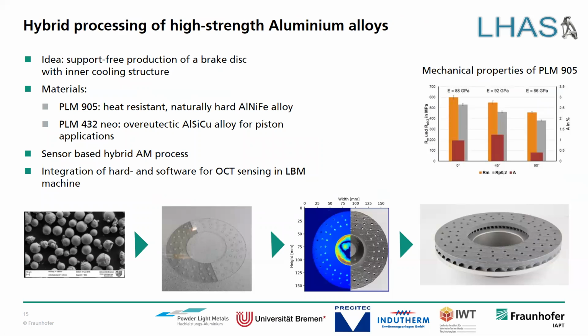A next project example that I just want to touch briefly on is the development of aluminium nickel iron and aluminium silicon copper alloys, also for automotive applications. In this case, the specialty of this project was that we had a hybrid approach. So we combined a conventionally manufactured base part that we included into our SLM system. And we printed the functional structure here made of the PLM 905 onto the base structure. And the main process task was here to precisely position the laser so that you don't get inaccuracies in the print process when joining the SLM part to the base plate.